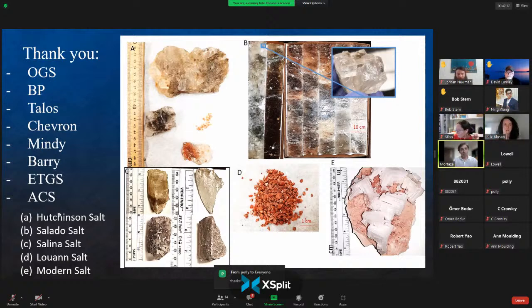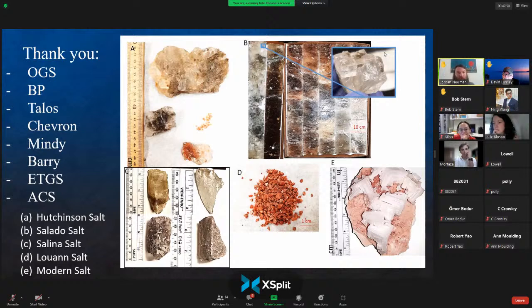Great. So Jordan, go ahead. A couple quick questions. One, we have the same XRF as you. On my best day, under perfect conditions, where I've had a balanced breakfast and everything's just right, the best I can get is about maybe 0.5% error bars. So basically it's more used for qualitative than quantitative analyses.